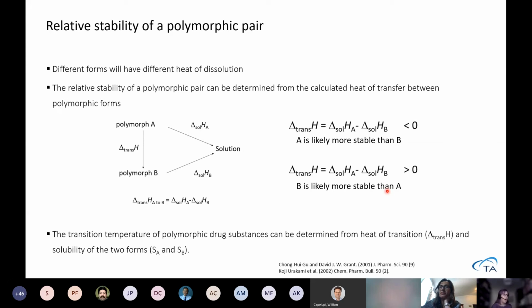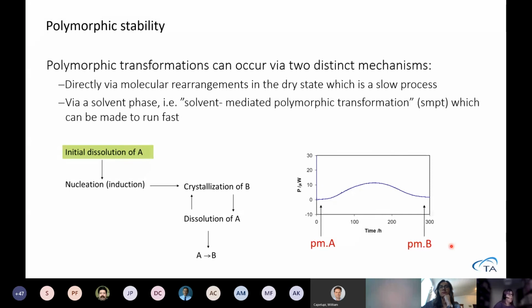And if you have the solubility of the two forms, you can also calculate the transition temperature. At what temperature will this drug transform from A to B or B to A, depending on which is more stable than the other. This is described more in these two papers that came out approximately simultaneously, that describe two different approaches to calculate the transition temperature.